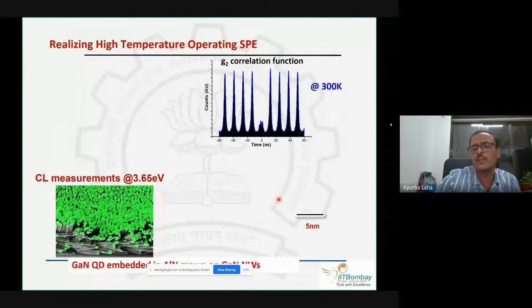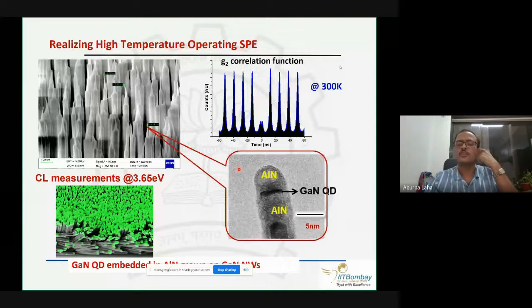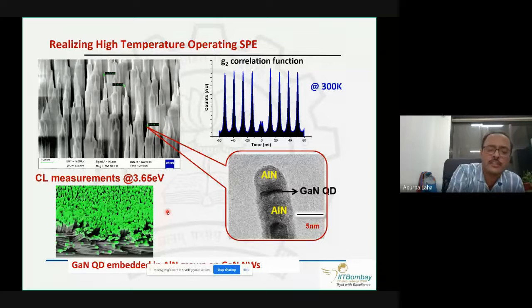You can see ultimately we are looking for generating the single photon source, and G2 correlation is one of the ways to look at photon correlations, and we see some of our nanostructures or quantum dots placed on gallium nitride nanowires truly show strong G2 correlations at room temperature. And finally, you will see the cathodoluminescence of those nanowires. This green is just a representation. It is not a green tube, because this is emitting UV light with an energy of 3.65 electron volt, and it is primarily confined only at the tip of this nanowire, you can see here.